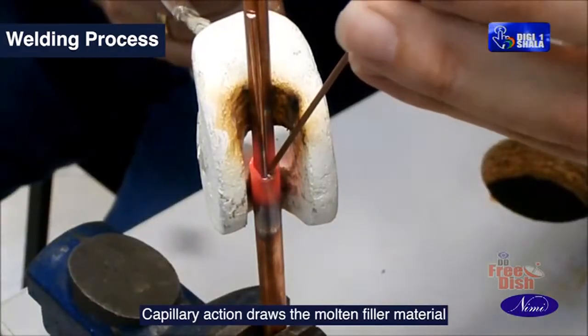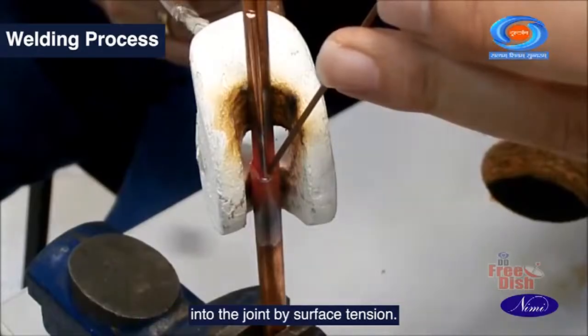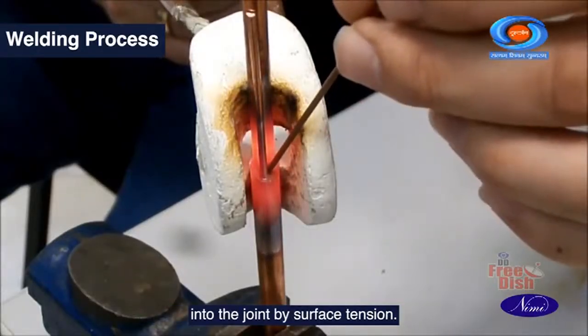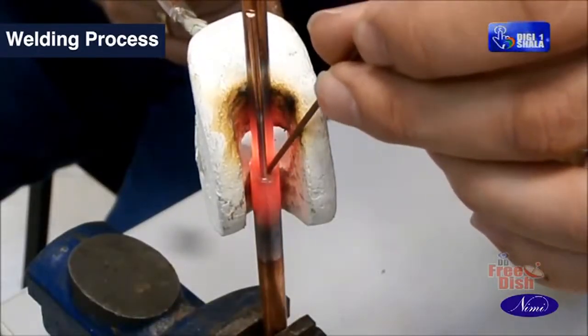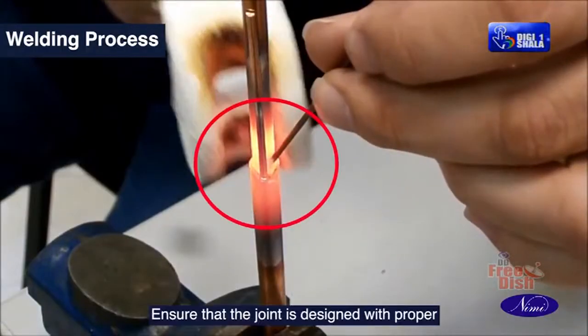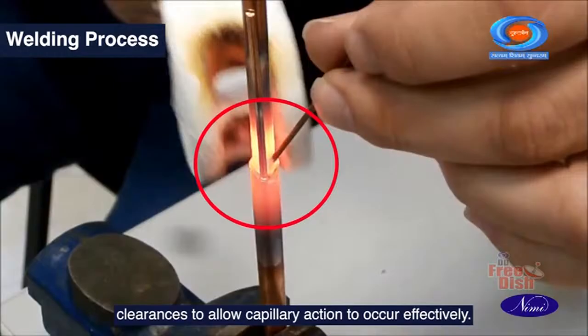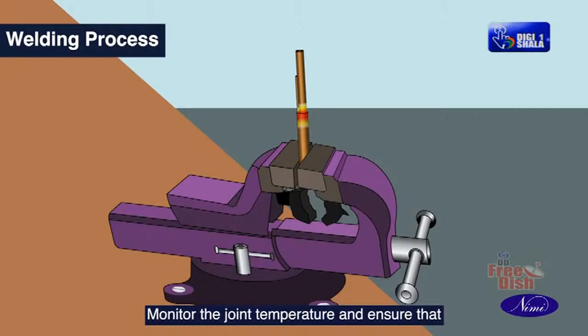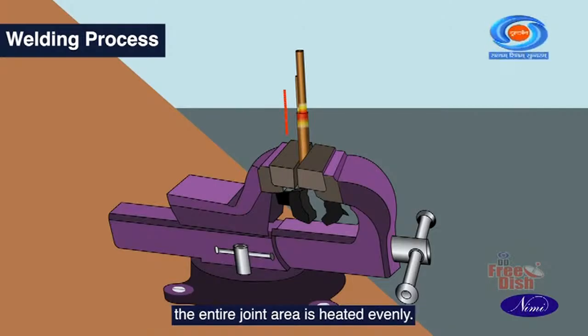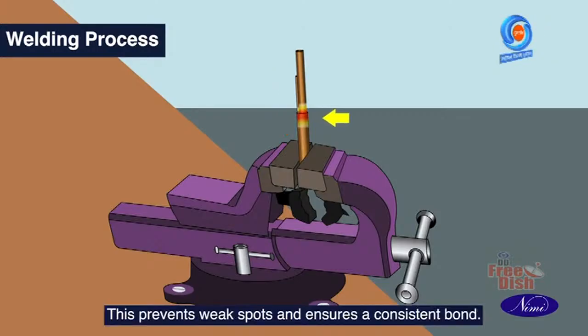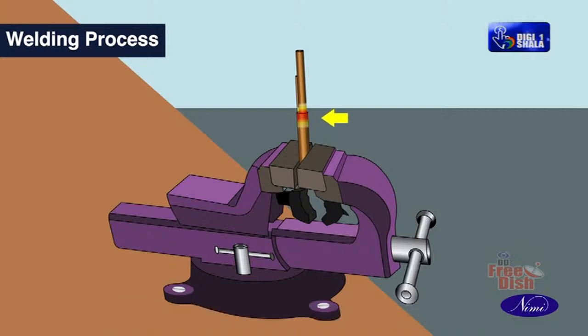Capillary action draws the molten filler material into the joint by surface tension. Ensure that the joint is designed with proper clearances to allow capillary action to occur effectively. Monitor the joint temperature and ensure that the entire joint area is heated evenly. This prevents weak spots and ensures a consistent bond.